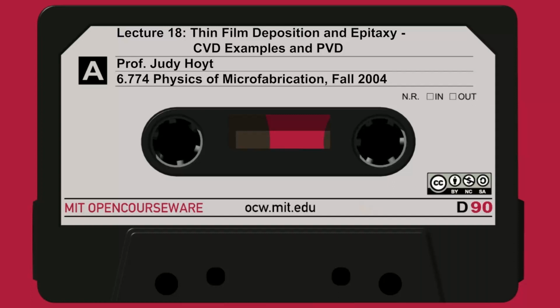Silicon nitride can be put down by an LPCVD process, as well as, as we talked about last time, plasma-enhanced CVD, and this is becoming more and more common. For low-pressure CVD, there are two different types of reactions that are commonly used. Silane is reacted with ammonia to create silicon nitride. The other one, the most common one, the one that's used here at MIT in LPCVD, is to use dichlorosilane, react that with ammonia, and obtain silicon nitride. This reaction is typically deposited to get reasonable deposition rates at around 800 degrees C.